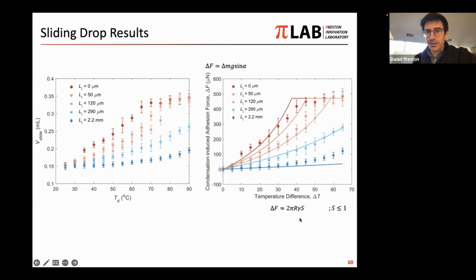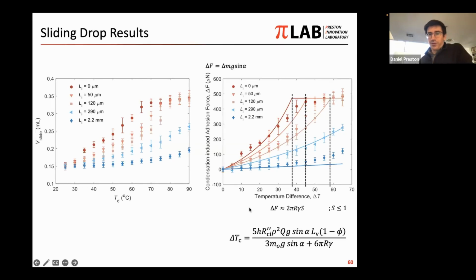In this case, the delta F is related to this fraction of filled-in unit cells on the surface. We can also find that this fraction of filled-in unit cells at the surface hits 1 at different temperature differences for different insulation thicknesses. And so we see these cusps, and we can correlate them to temperatures on the x-axis. If we do that, we can define what's called a critical delta T sub C, where that transition occurs. It turned out that this was a really convenient way to non-dimensionalize the behavior.